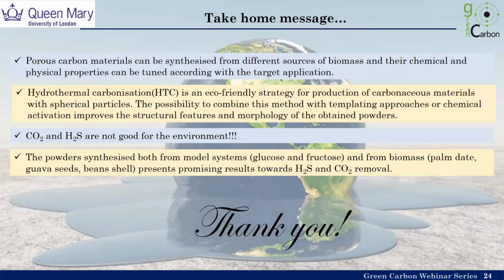And as a take-home message, I hope I managed to show you that porous carbon materials can be synthesized from a bunch of sources of biomass, and probably you already knew that, but their chemical and physical properties can be tuned according to the target application. We find hydrothermal carbonization an eco-friendly strategy, and that's why we use it so much in our lab. We produce carbon materials with spherical particles. We like the possibility to combine this method with templating approaches, because in this way we can improve the structural features and morphology, and we can have better powders.